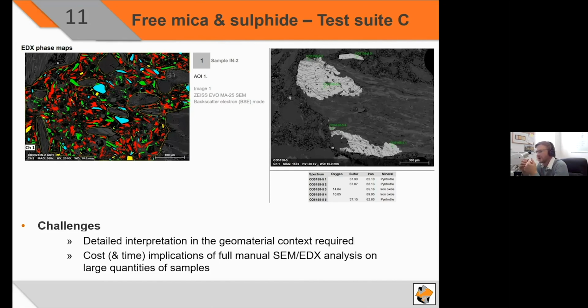Anything over 63 microns is suggested to be non-deleterious, as mica is a commonly observed mineral throughout these strata. But it's really the fine mica that's below 63 microns, which has a major issue on the performance of concrete in this application. On the right-hand side, we have SEM analysis to confirm pyrrhotite, that is equally applicable to County Mayo and County Clare type analysis, where it can be used to provide detailed confirmations of in situ oxidation.